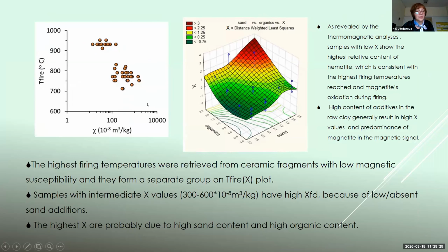rest of the samples. And this difference turned out to be due to the fact that the samples showing lower firing temperature contained the highest amount of sand additions and organics. So this difference in the composition of the samples governs the magnetic behavior as well as the firing temperatures.